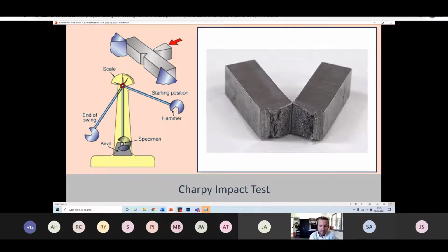So note, for example, in the specimen, in the top of this image on the left-hand side, that the specimen has been deliberately notched, and that's in order to drive the crack in a particular direction and to make sure that the energy that's been absorbed is being absorbed only through the process of that crack propagation event. Okay.